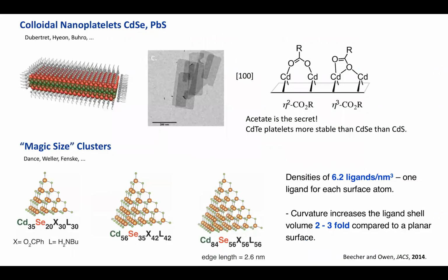All right, so I think, yeah, one last thing about this, which I'm trying to get the group to explore, is that in a colloidal nanoplatelet, my belief is that the same forces are at play. Okay, the reason these objects are stable is that they're highly curved and you can fit ligands around them. Benzoate works very nicely because it's flat. Anything bigger than that, those start to fall apart. Okay, it's packing density that makes that possible, and it stabilizes these objects.